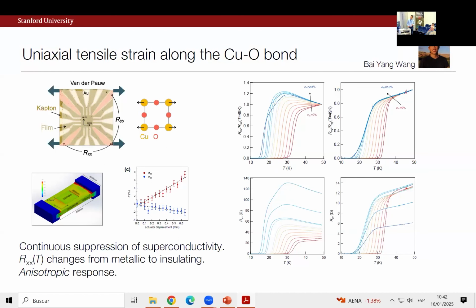So Bai, having designed this beautiful strain stage, was using it to study this problem. So he made a 1/8 doped 214 membrane. And this is a typical sample. In general, we're using inline or van der Pauw geometry. So here's a van der Pauw picture. And what he's doing is getting into a regime of basically uniaxial strain, so stretching in this direction. This is a finite element simulation.